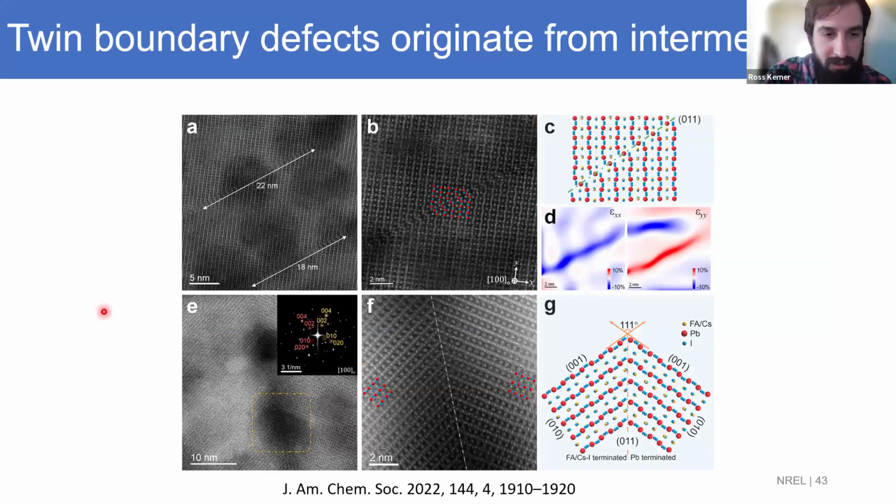Fairly recently, and going back a few years, there have been some amazing advances in how people can do TEM on these perovskites, and we're starting to get direct images of defects, which is super cool. This TEM was done by Yan Zhou. In this figure particularly, he sees this twin boundary exactly along the (111) plane. So that's probably just a single twin face sharing, and then he sees other inclusions that, if you zoomed in on this area, are basically like a 4H type defect, just one layer of face sharing, two twin boundaries really close together.